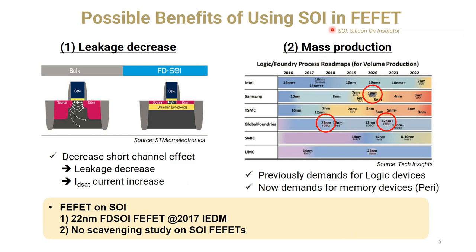And also in this study, we used SOI in the FeFET. SOI, as you already know, is silicon on insulator, and this silicon on insulator wafer by itself has a benefit. The benefit is a leakage decrease. The SOI wafer has the BOX, buried oxide layer, and this BOX layer decreases the leakage from the source to drain and from the source and drain to the body. So if we just use this SOI wafer, we have a leakage decrease, and then it can increase the on current. So there is a huge benefit with this SOI.